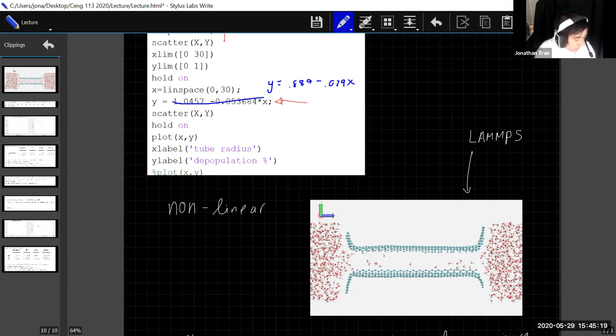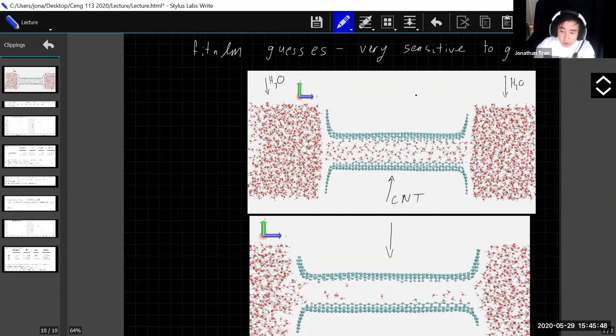And basically, within this sort of 3D modeling package, you can create your own variables to define different things. In this case, to count the water in the tube, I run a system without my magical depopulation construction. Typically what happens in a carbon nanotube is that the tube will automatically fill. There's nothing to prevent it from filling. It's thermodynamically favorable for it to fill, so that's just a natural consequence. Once it's filled, I can run this over a long time span and then calculate the average number of water molecules on the inside of the tube.